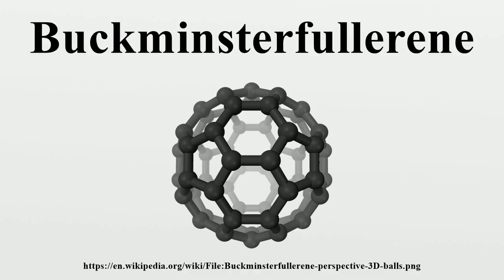C60 tends to avoid having double bonds in the pentagonal rings, which makes electron delocalization poor, and results in C60 not being superaromatic. C60 behaves very much like an electron-deficient alkene and readily reacts with electron-rich species. A carbon atom in the C60 molecule can be substituted by a nitrogen or boron atom yielding a C59N or C59B respectively. Solution. Fullerenes are sparingly soluble in aromatic solvents such as toluene and carbon disulfide, but insoluble in water.